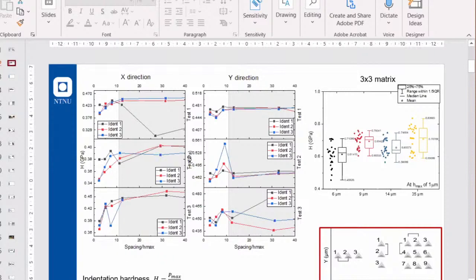And when doing this, we actually noticed that around a separation of 14 microns between the sequential indents is when we start to get relatively similar data, which then means that we can space our indents by 14 microns or greater, allowing us to have comparable data and therefore a larger statistic within our small samples. And that's the end of mine.